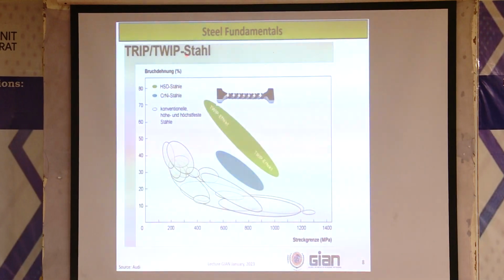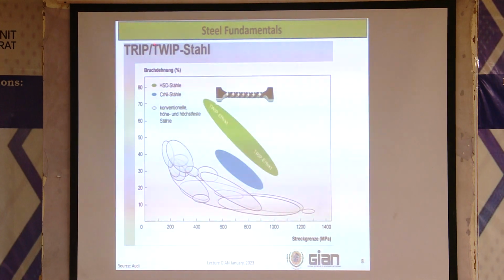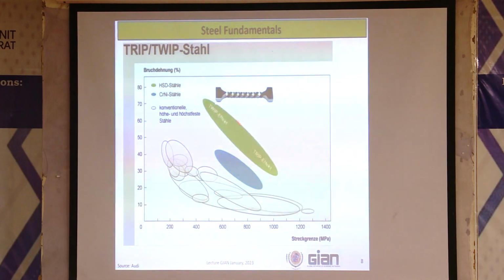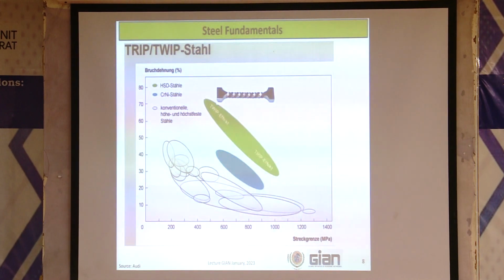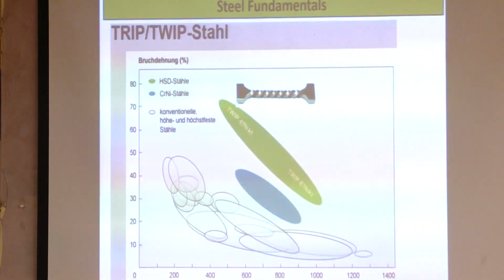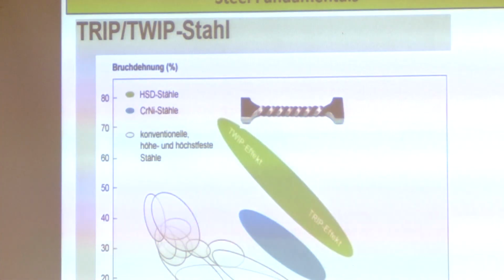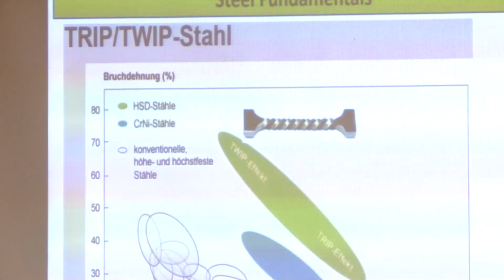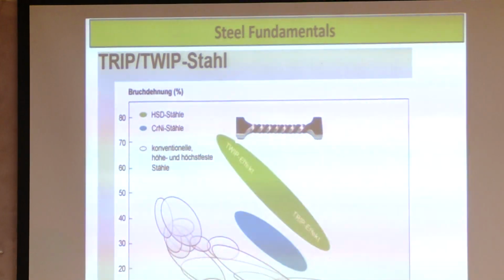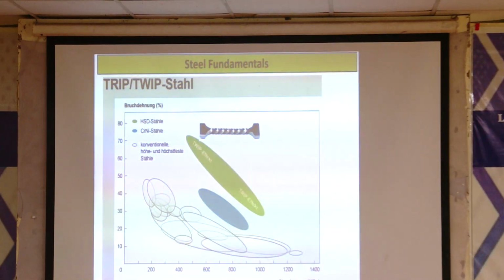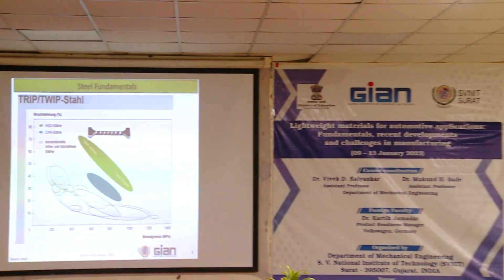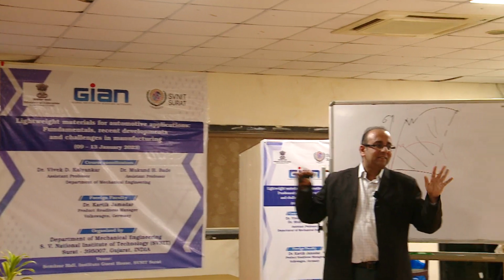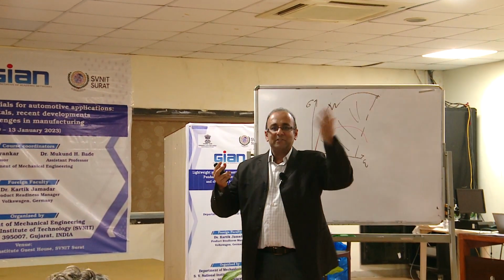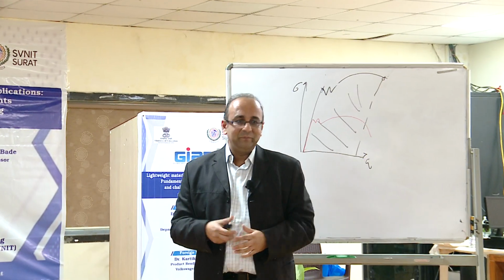TRIP steel or TWIP steel: transformation induced plasticity or twinning induced plasticity. Like this is a twinning. Normally we have a higher elongation because here we have not ferrite but austenite, retained austenite and martensite structure. Austenite, as we know, is a very good formable material. Better than austenite, nothing exists. Unfortunately, we are not living at 700 degrees centigrade, else I wouldn't have needed any other steel, I would have only used austenite. High strength, high formability, everything very good.